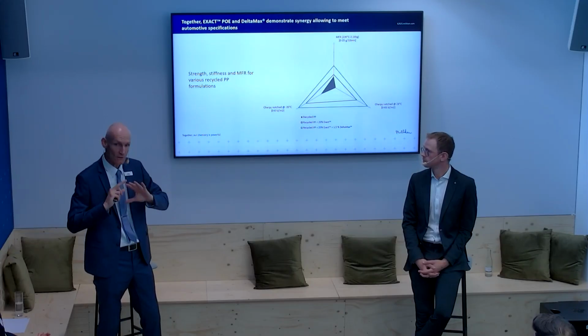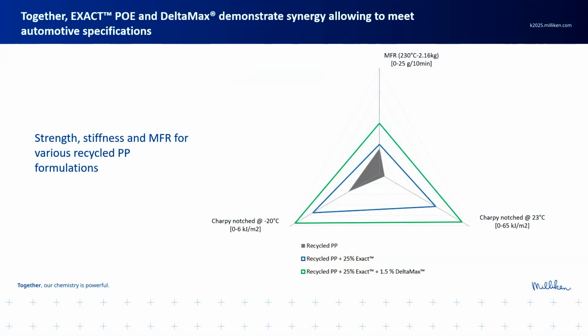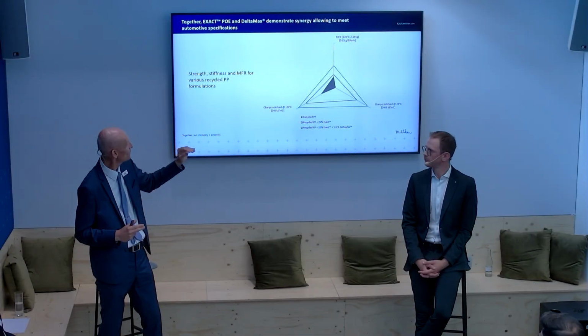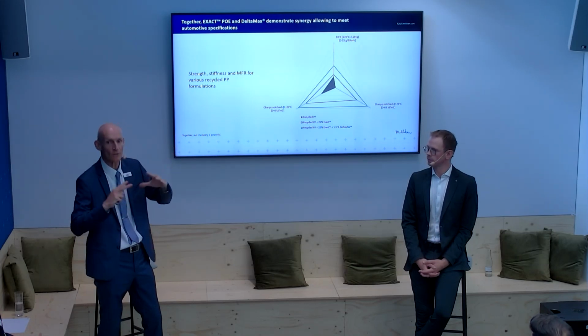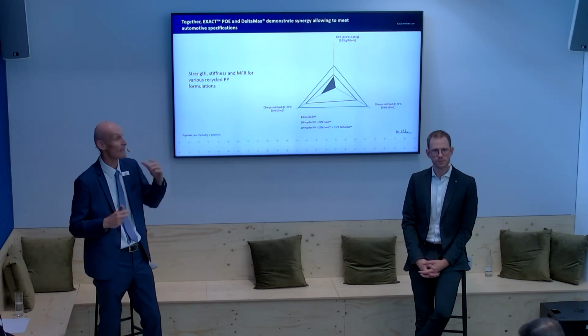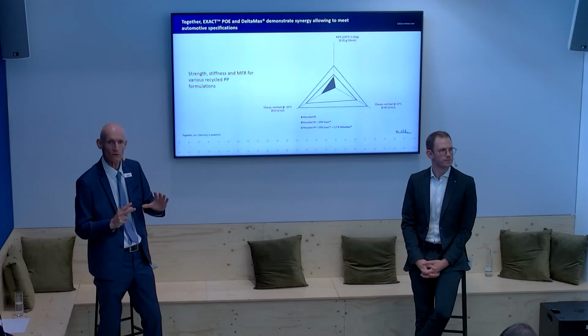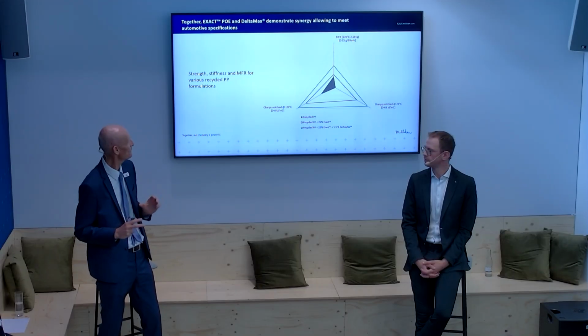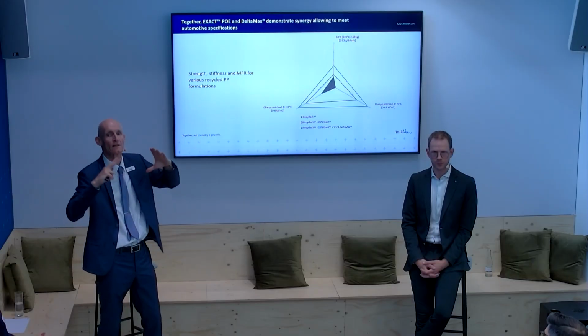So you see in our story, in summary, the basic properties of the recycled polypropylene, a very low base grade, are the gray triangle. And we're going to expand that in terms of flow to the top. First blue, then green, blue with the Exact, and then green, the Exact, and the Delta Max. And we're going to do that also for notch Charpy, the impact properties, at room temperature and at low temperature. So we're not going to sacrifice one property for the other. We're going to use the synergy and expand the usability.